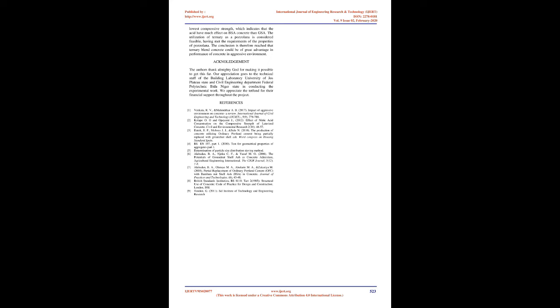It was also observed that the combination of 10% at 28 days, and 30% at 56 days binary OPC/BSA subjected to MgSO4 gave the least compressive strength in all cubes. This may be attributed to the deficiency of SiO2, Fe2O3 in BSA and its high vulnerability to acid attack.